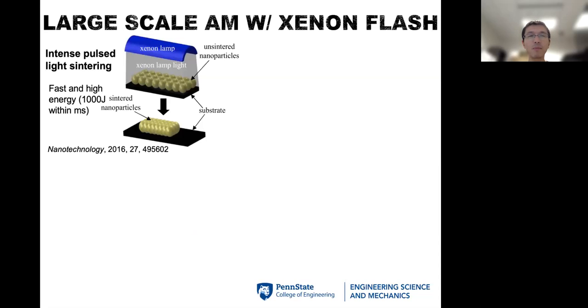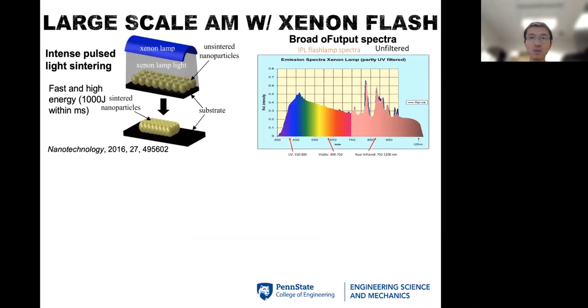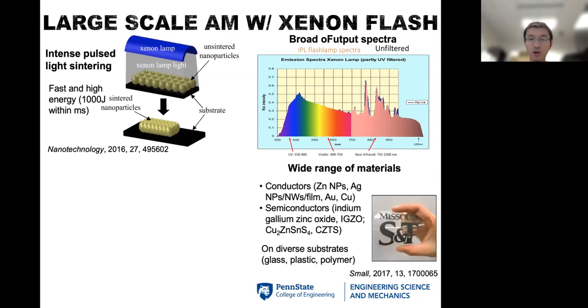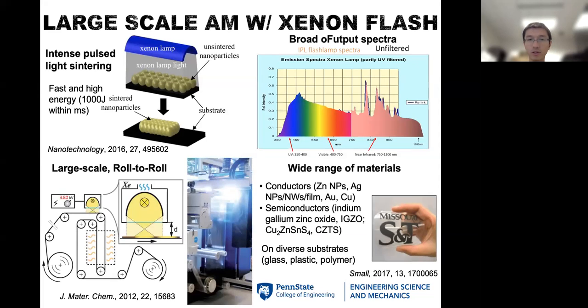And today, I'm going to focus a bit more on a different manufacturing approach, the so-called xenon light. Xenon light is very useful because it provides super high energy and is super fast to operate. It can be very useful to sinter nanoparticles together into a conductive pathway. This works with a lot of different nanoparticles because of the wide band of xenon light, from 200 nanometers to 1200 nanometers in terms of spectrum. That's why you don't need to modulate the laser as with others, but rather you can shine the xenon light over zinc, silver, copper, gold, and other different semiconductors on diverse substrates, from glass to plastic to polymer. And this can also be low cost if you work with roll-to-roll application.